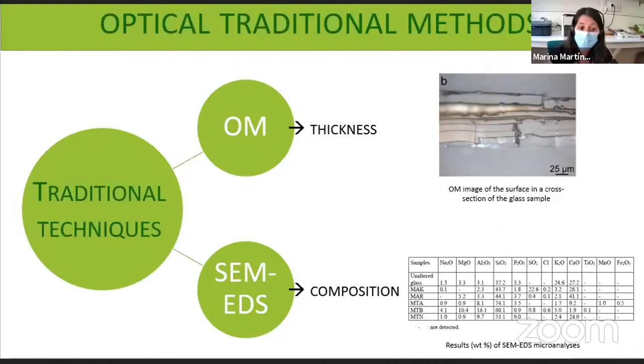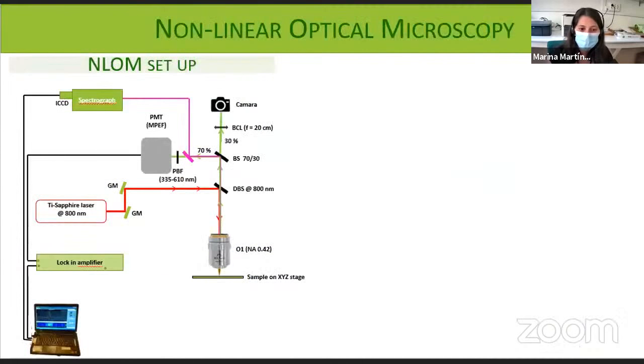These techniques are destructive. Techniques of nonlinear microscopy were recently introduced into the study of cultural heritage, particularly in the modality of multiphoton excitation fluorescence. Based on excitation with an ultra-fast and ultra-short titanium sapphire laser, the excitation of the material takes place in the focus where the nonlinear processes are induced. The collection of the multiphoton signal is carried out in the reflection mode through the same objective and then sent to the photomultiplier.